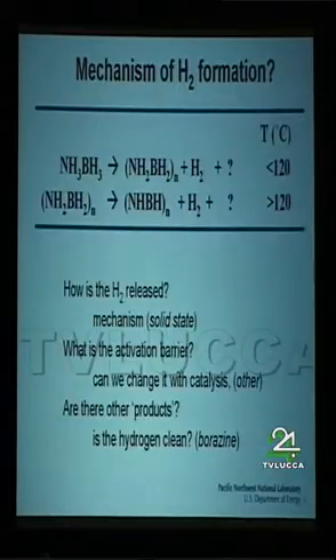We obviously weren't the first ones to think about looking at this. There's been some very, very elegant work that's come from Freiburg, from Gert Wolf and his colleagues, who have been looking at this for probably around 5 years now as a potential hydrogen storage material. And the material is stable to air. It doesn't flame up. You can dissolve it in water. If you add acid, it starts to decompose. But in neutral water, it's quite soluble and quite stable.